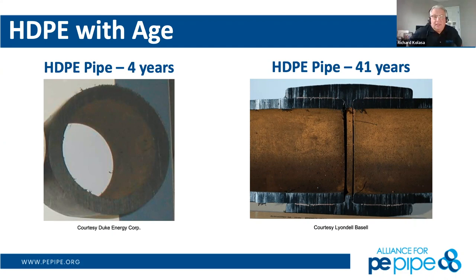Yeah, it really doesn't, because nothing really impacts polyethylene, especially in water systems, even with oxidizers present. In this particular case, this was supplied by LyondellBasell. This picture is actually about 10 years old, so this line is still going. It has an electrofusion that's 10 years old, and the pipe is 41 years old. What you're seeing is just a rust buildup, some kind of high iron content in there, but you can see the nail scratch that easily comes off. So it doesn't support any growth and nothing adheres to it.